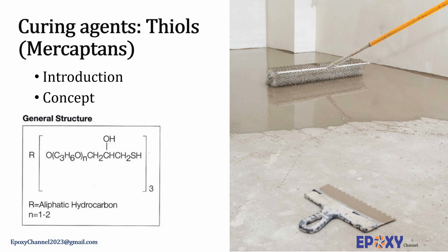One of the problems associated with amine hardeners is that they can take up to a couple of hours to cure at ambient temperature depending on the structures, with the fastest amine still only curing in 30 minutes to an hour. Mercaptans are curing agents for epoxide capable of being cured in very short times, for example, minutes or less. The sulfur in thiols readily reacts with the epoxide group even at ambient or subambient temperatures.